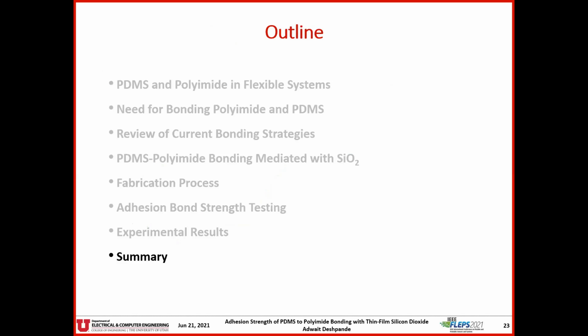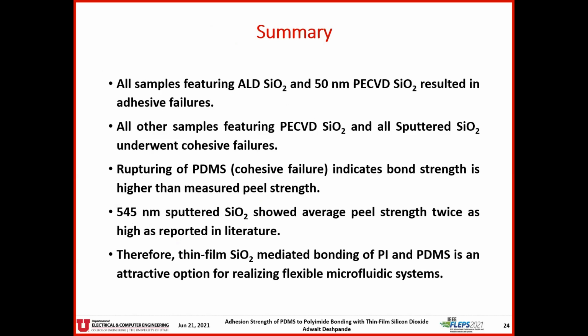To summarize, all the ALD SiO2 samples and 50 nanometer PECVD SiO2 samples resulted in adhesive failures. All other PECVD SiO2 samples and all sputtered SiO2 samples underwent cohesive failures. Rupturing of the PDMS, that is cohesive failure, indicates that the bond strength is or may be higher than the measured peel strength. 545 nanometers of sputtered SiO2 showed average peel strengths twice as high as reported in literature. Therefore, thin film SiO2 mediated bonding of polyimide and PDMS is an attractive option for realizing flexible microfluidic systems.